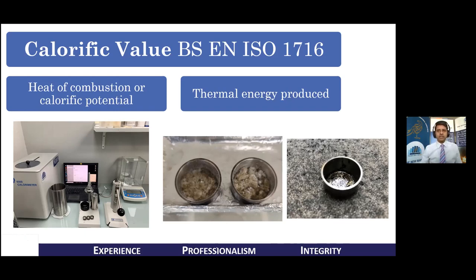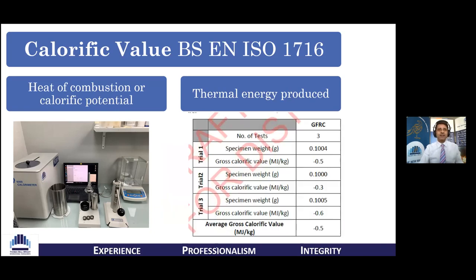of that material. So a test specimen of a specified mass is burned under stabilized conditions at constant volume in an atmosphere of oxygen, which is inside a sealed bomb calorimeter. And when it is completely burned, the amount of energy it releases heats the water jacket, and then the delta temperature is measured. And based on a calculation, the heat of combustion, which is the amount of heat energy that is produced, is quantified. And hence, we arrive at the gross calorific value of the three tests that we do.